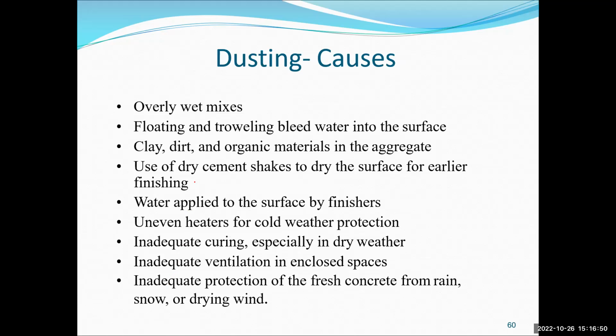Dusting, causes of dusting. If you rub your finger or thumb against the concrete and you feel the finger is full of dust, this is dusting. There are some fine particles that are not bonded in the concrete because of an overly wet mix at the very top, or floating or troweling while you have a bleeding surface. You remember we talked about the bleeding surface at the top here. If you start disturbing it, then you end up with dust at the top. You use a lot of dirt or clay.